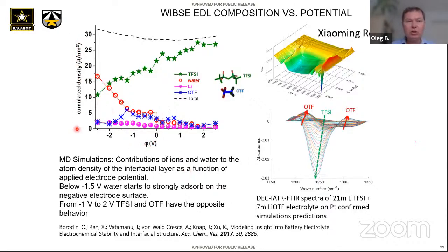Let me get a summary for this. If I look at cumulative density only in this inner Helmholtz layer, the water fraction stays approximately the same until about 1.4 volts versus potential of zero charge. If you say the potential of zero charge is approximately 3 volts or so, then that would be 1.5 volts versus lithium. Below those, titanates and others will get challenging because lithium is going to be coming in.